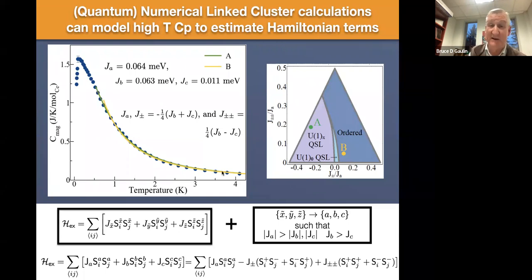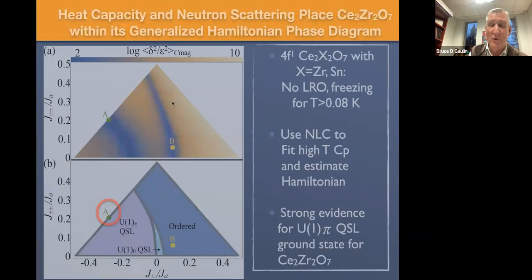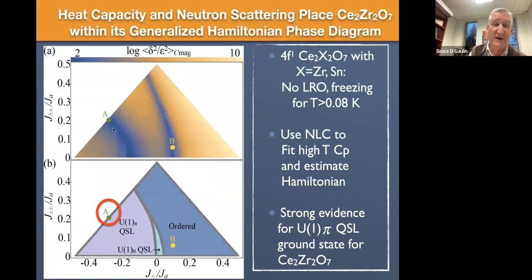But you can get a unique fit or a very good fit to this high temperature part of the heat capacity. Okay, and actually, if you go through this exercise, and I'll give you a reference to show you how to do that, it turns out that the best fit is actually this A parameter. There's actually 2 regions where there are reasonable fits, but for the A parameter, 2 of the 3 exchange parameters are almost the same, and the third is quite a bit weaker. Okay, and so if you go through that exercise, there's actually 2 regions in this phase diagram where you can get a good fit, and those are shown by these sort of bluish bands. And the best fits in each of these bands is at position A and position B. But the best fit overall is at position A.